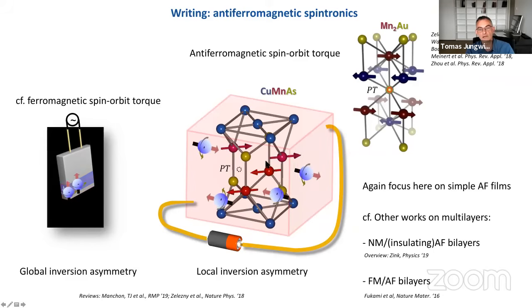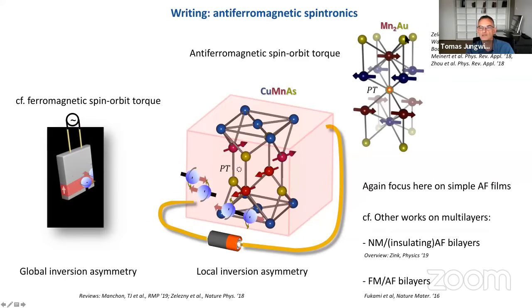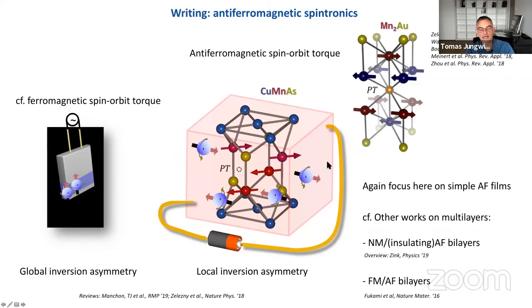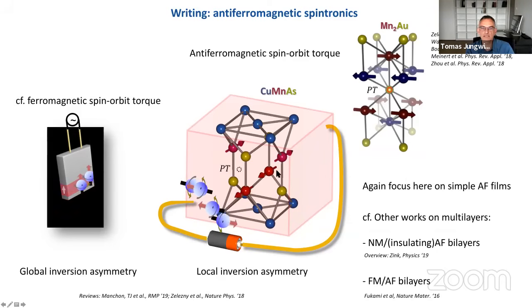So we have in crystals with this symmetry, and copper manganese arsenide is not the only example known. We have also manganese two gold, which has the same symmetry properties, where we can electrically generate non-equilibrium spin polarizations, which are commensurate with the staggered magnetic order, and can therefore manipulate it as efficiently as the spin-orbit torque in ferromagnets. Now again, I emphasize that this is a bulk effect that happens in simple antiferromagnetic films.